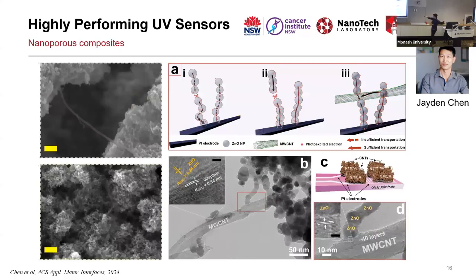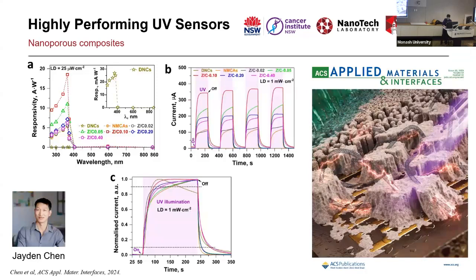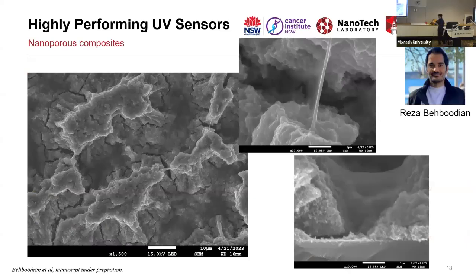Of course, we added carbon nanotube to make sure that, for example, clusters that might not be connecting with each other could be linked: with the carbon nanotube we could create great bridges from one cluster to another. This one was selected as a cover photo of Applied Materials and Interfaces. Because of the conductivity of carbon nanotube, we also got significantly higher electrical signal, or sensing performance, from our sample. And as I said, it can go on and on. We can add anything that you want.